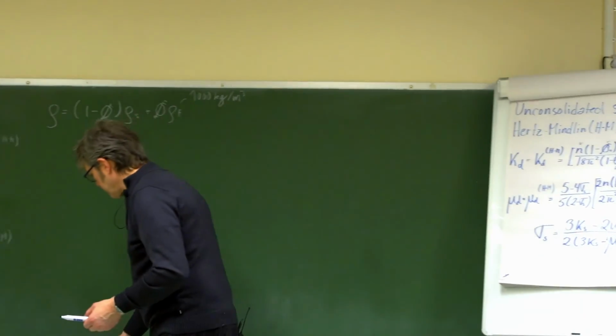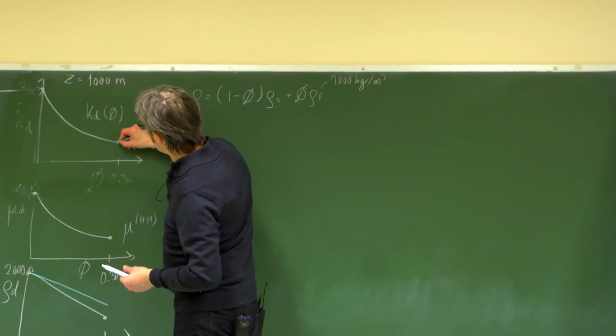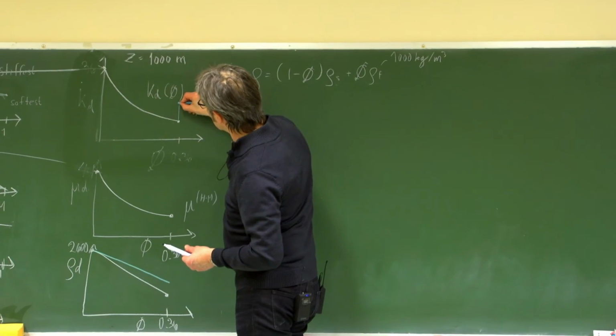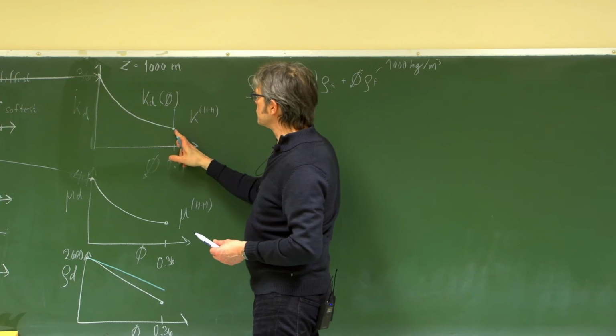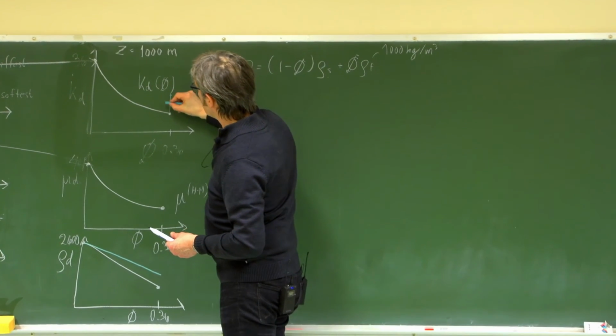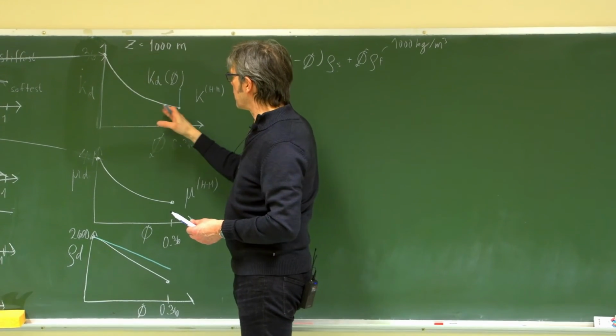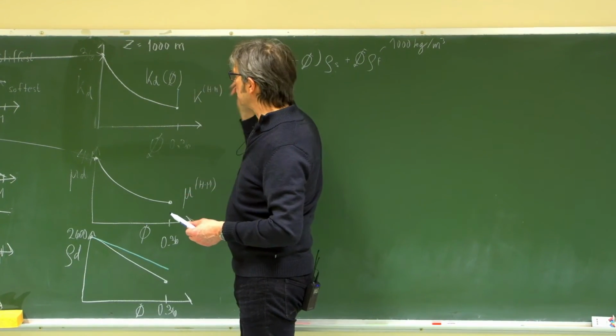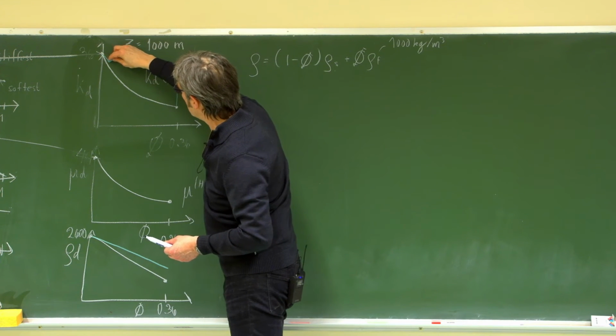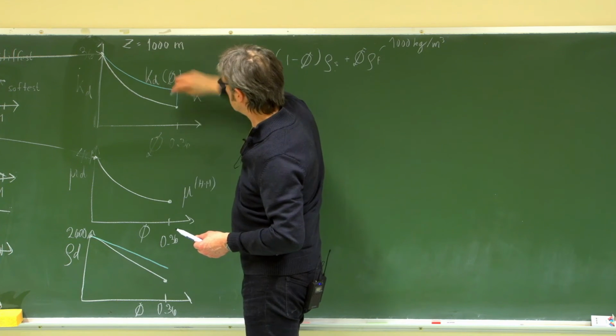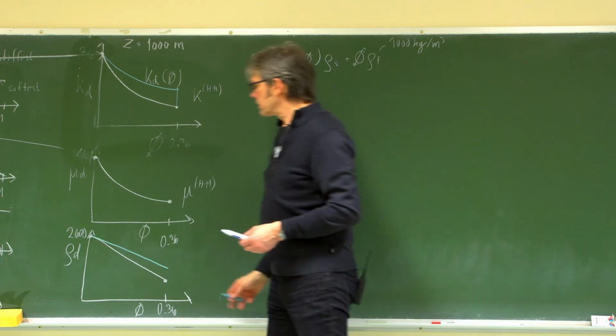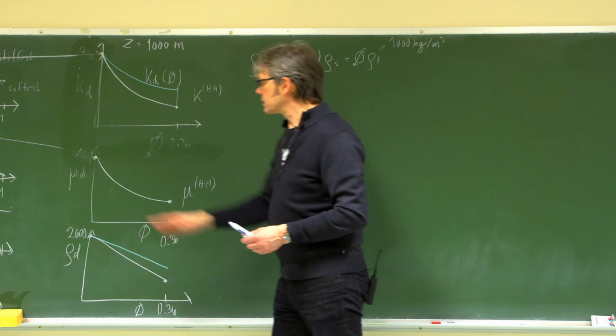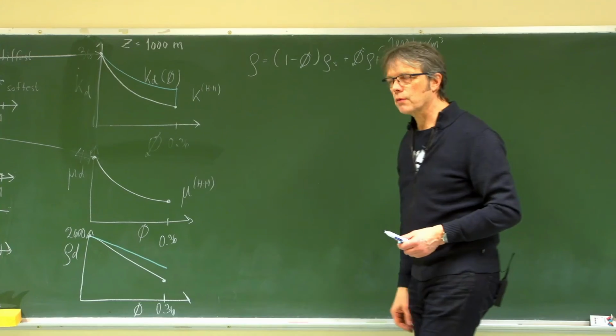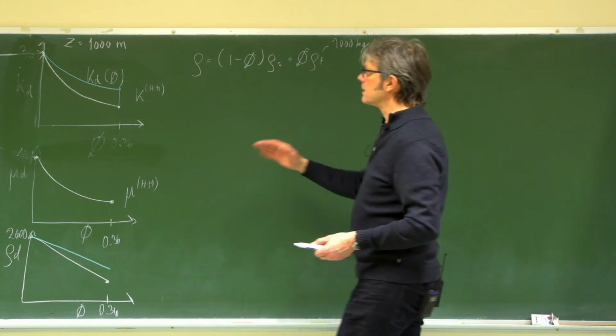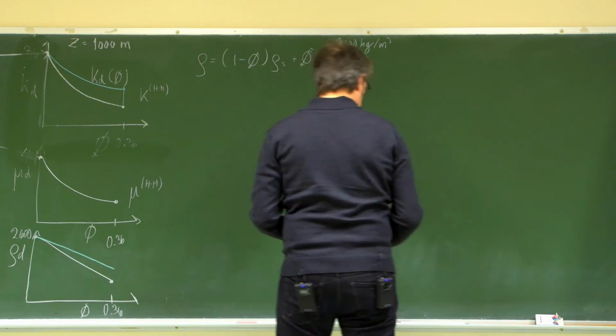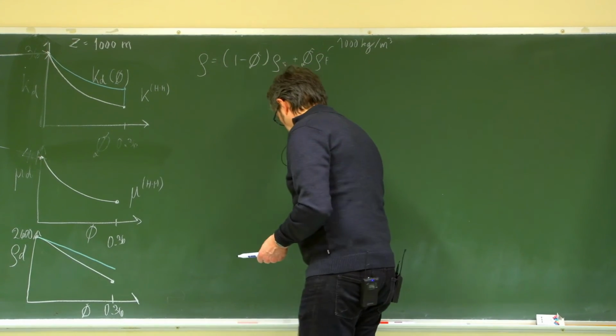So what happens here? Well, when I add some fluid inside here, this point would just go up here. Large porosity, large fluid effect, and so forth. I can just take the Kd and porosity and plug into the Gassmann equation, and then finally I would end up with a fluid effect like this. Fully water saturated. The shear modulus unaffected, so I don't have to care about that one. And now I can start adding different fluids or different saturations. So let me add 10% of gas here.